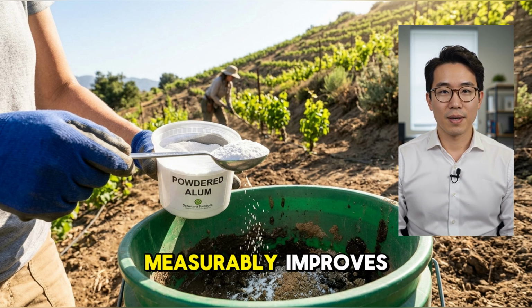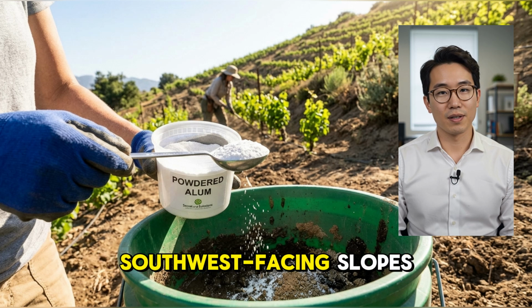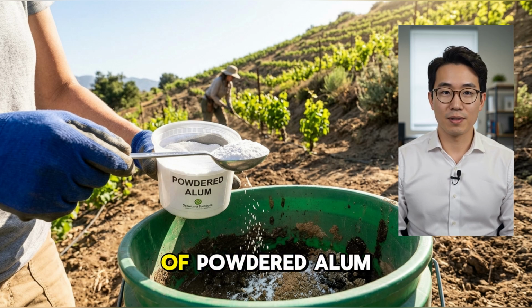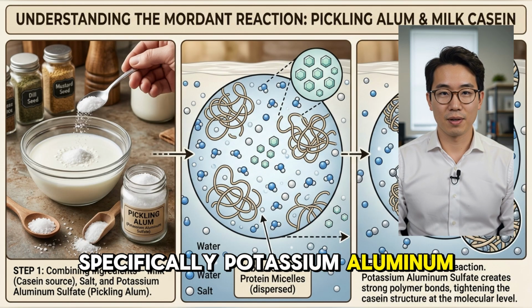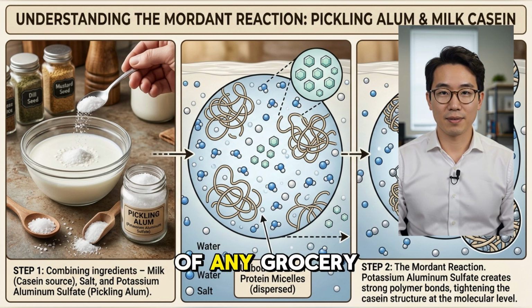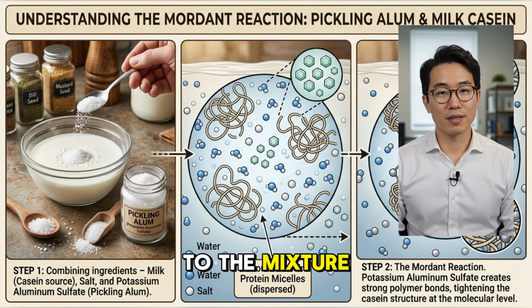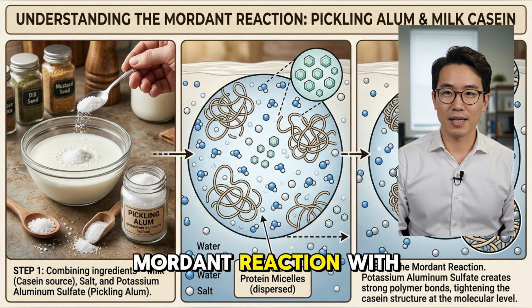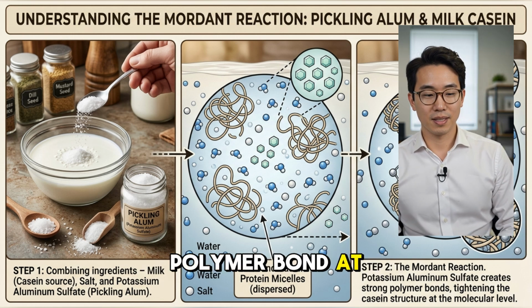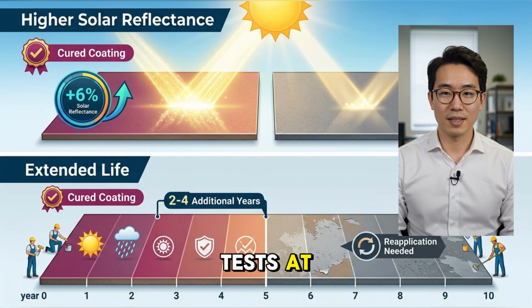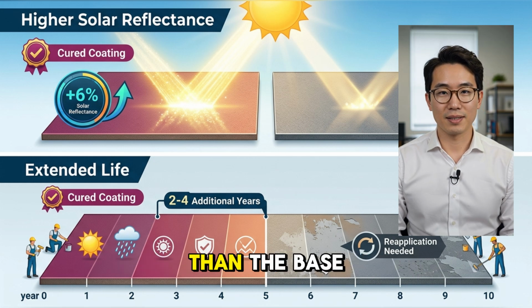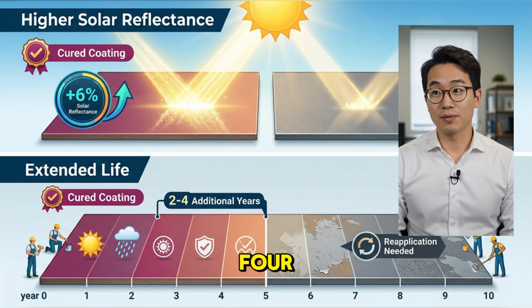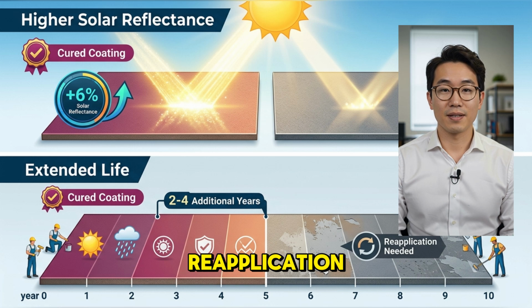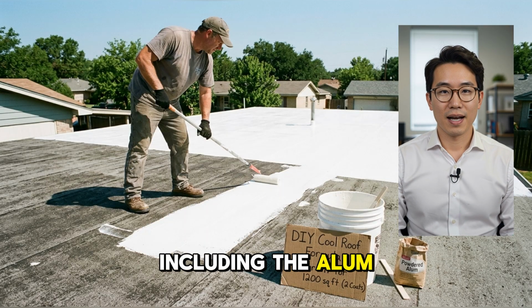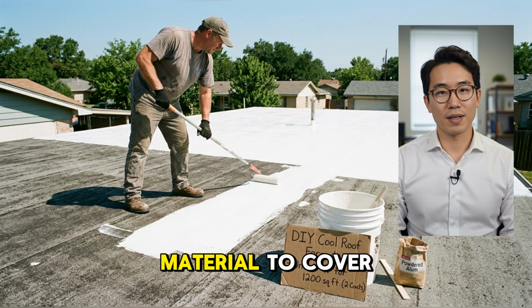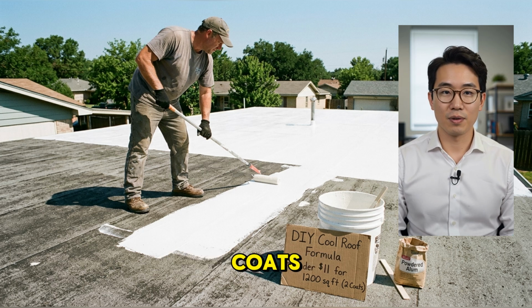There is one refinement that measurably improves performance on south-facing and southwest-facing slopes. Adding 2 tablespoons of powdered alum, specifically potassium aluminum sulfate, sold in the spice aisle of any grocery store as pickling alum, to the mixture alongside the milk and salt creates a mordant reaction with the casein protein that tightens the polymer bond at the molecular level. The cured coating tests at approximately 6% higher solar reflectance than the base formula and survives 2 to 4 additional years before reapplication. The total cost of the complete formula, including the alum, is under $11 for enough material to cover 1,200 square feet in 2 full coats.